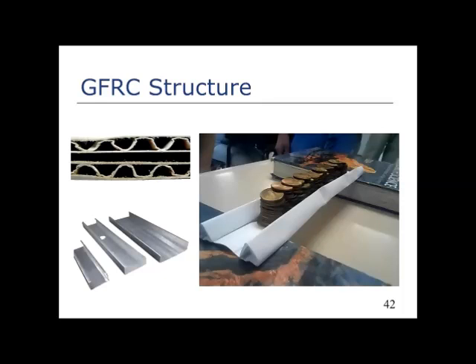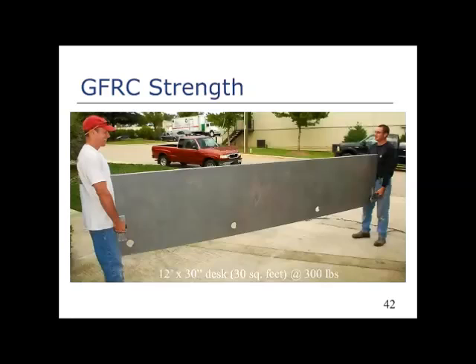And this is how typically GFRC is made. It's a thin shell with molded edges, and those edges give it the stiffness. Now, we use less material, but it's more complicated to make, so that's the trade-off. And so the casting process, instead of simply building a box and filling it full of concrete and having it solid and heavy, we line that box with a thin shell using less material, so it's more efficient, but it's more difficult and we have to be more careful about how we make it. But we can do some pretty cool things with it.